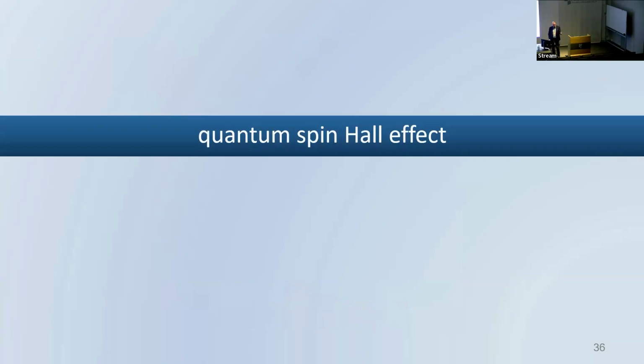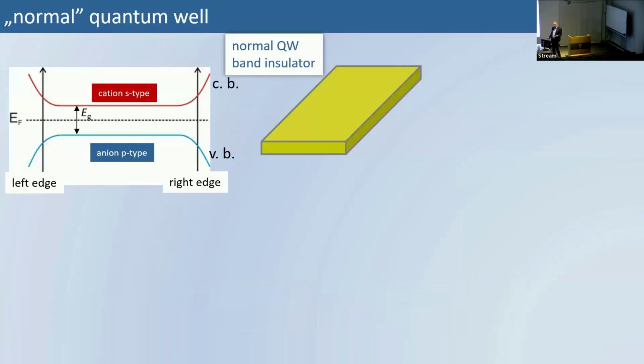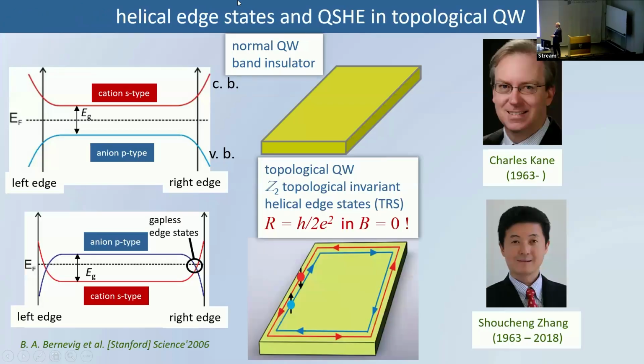And now we turn to a new effect, not the quantum Hall effect, but the quantum spin Hall effect. And now we speak about a two-dimensional system, about a quantum well. And we know that in a standard system we have cation states here, anion states here, and you have a gap between. But if you take now a topological system, the situation changes, because now you have anion p states above cation s states, and you have this topological invariant which is not zero, and you put it with vacuum which has topological invariant zero, you expect boundary states. Also, you can think about stitching of the wave function, and you will get the same results.